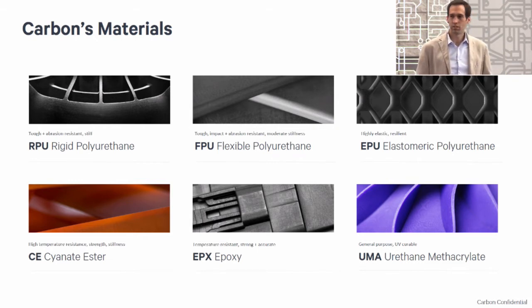Our cyanate ester material is a high temp material that performs very much like a 15% glass filled nylon. And our epoxy material is a material that performs a lot like a 20% glass filled PBT, which is very good for when you need good temperature resistance, but also a strong material and a material that's going to be quite accurate for the printing process.